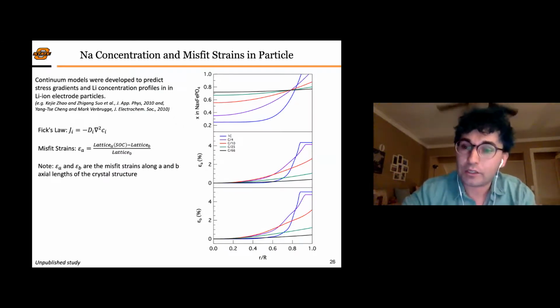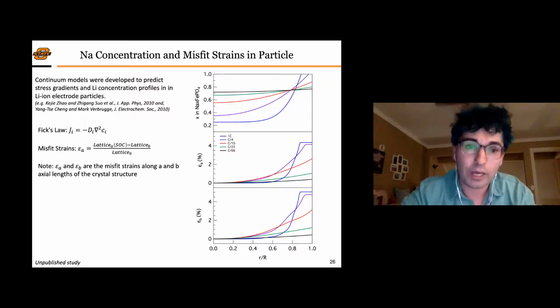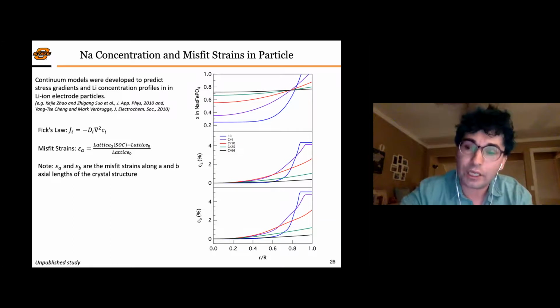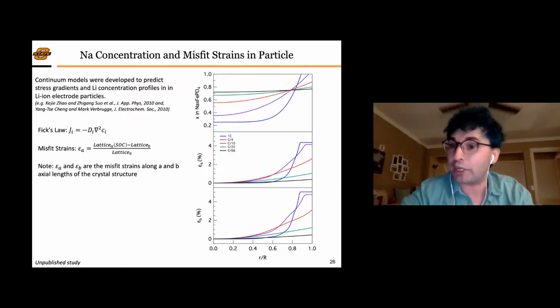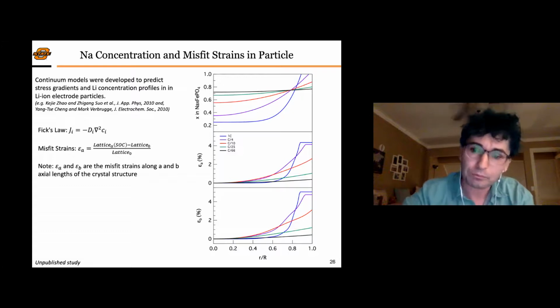The particle strains and stresses were previously predicted by various groups in the early 2000s. I just picked two groups here for reference. Simply, you use Fick's law to calculate the concentration profile. From there, you can use the XRD data to calculate the strains, and you can use the mechanical properties to calculate the stress profiles.